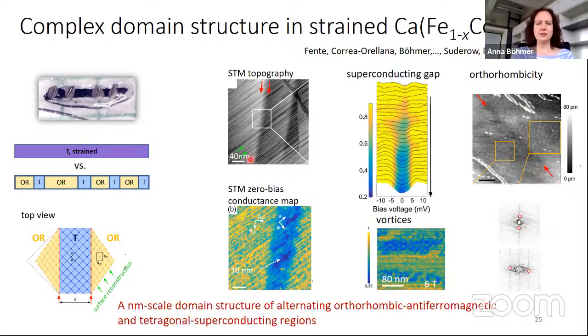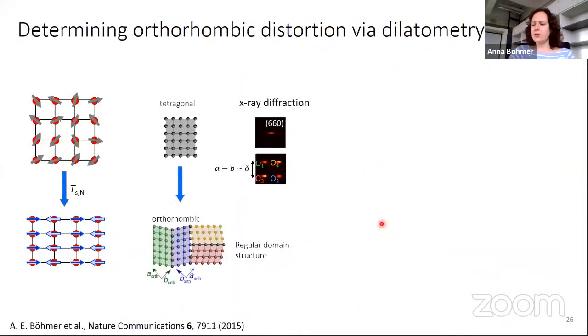So what we find here is a really nanometer scale, a very small, interesting domain structure of the same material being in different phases, being in different states. One of them is this orthorhombic, this distorted stripe-type antiferromagnetic one, and one is superconducting. And that's quite cool. Maybe we can think of some interesting consequences there. Then, okay, I'm going slow here, but I'll skip a few things. There's just some interesting things to talk about.